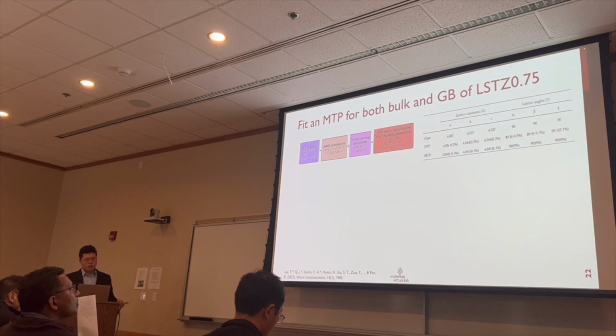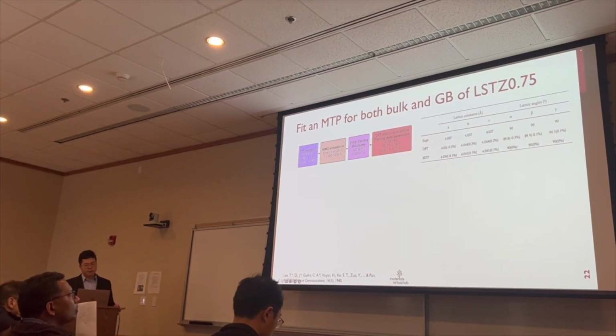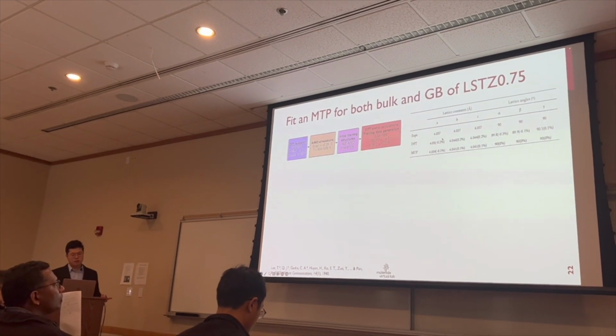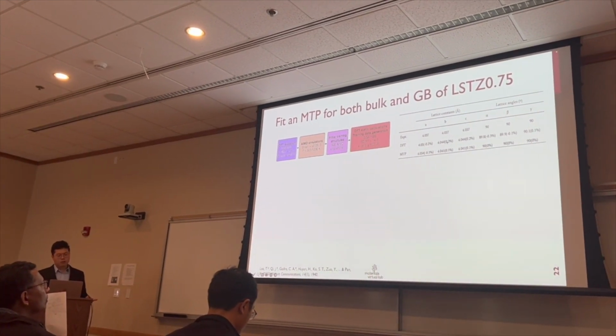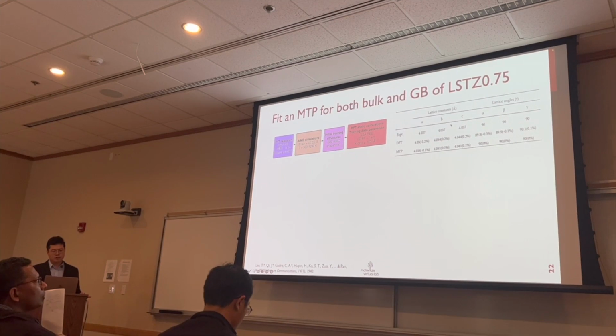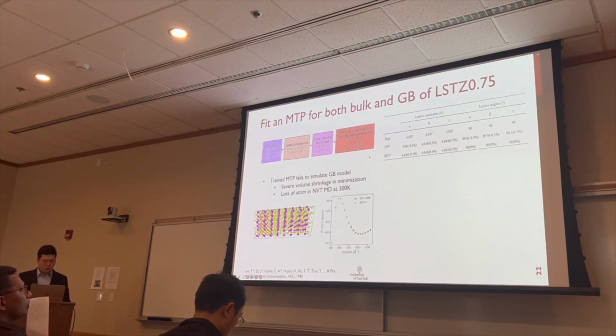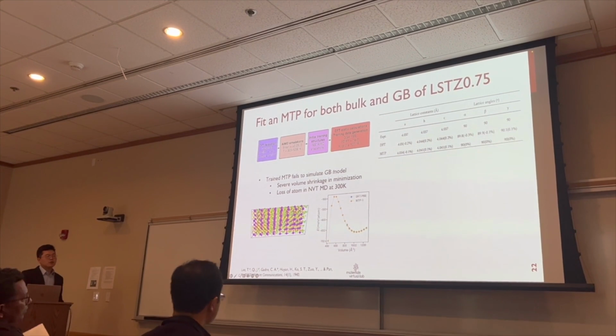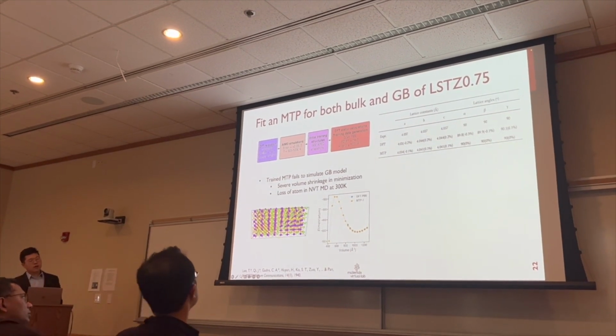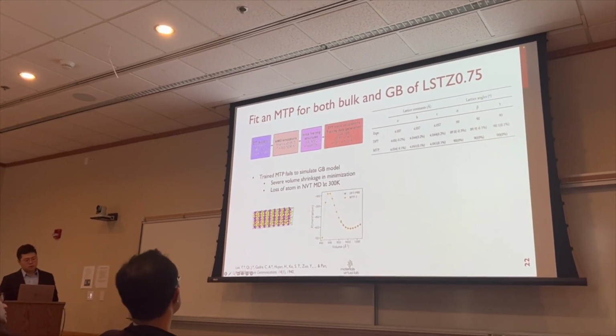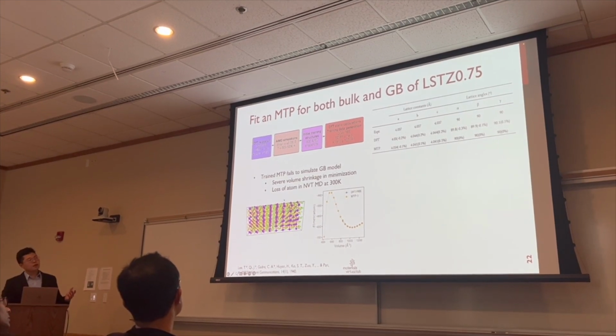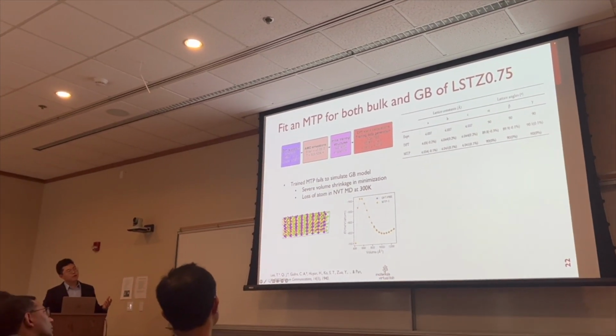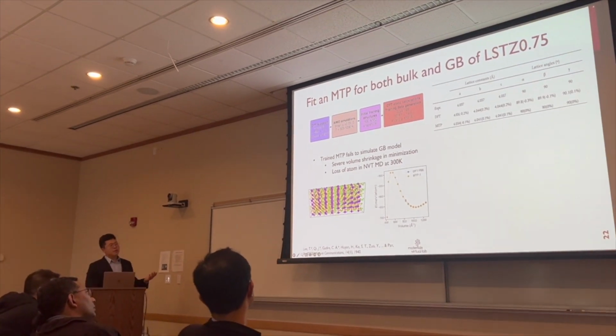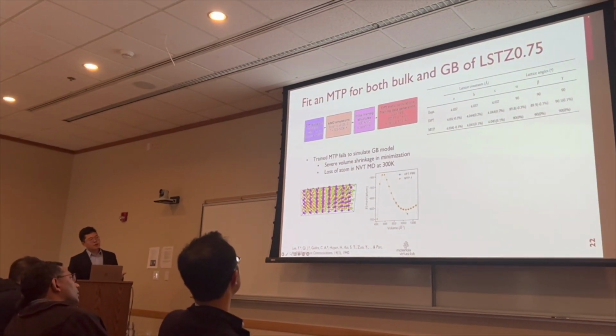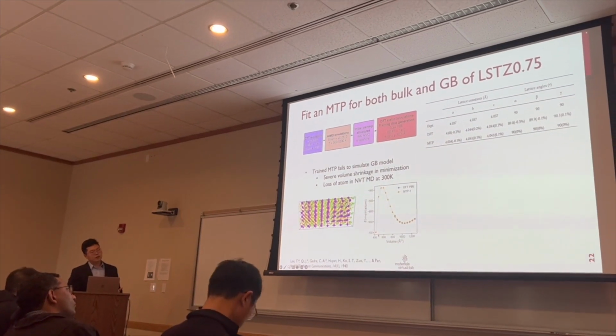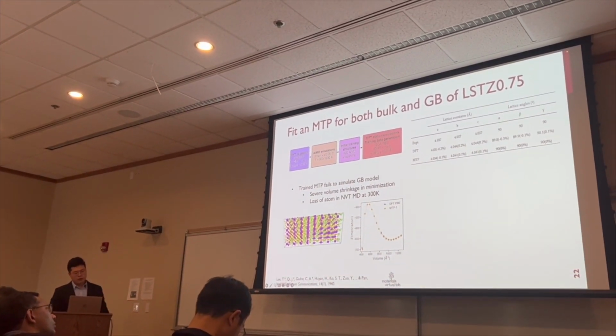And here we use the PBE functional because we see that the DFT result with PBE functional already has very good matching with experimental results in terms of lattice parameters. However, when we apply this moment tensor potential to simulate some practical scenarios, which are grain boundary models, we can see that there's some unphysical behavior. Here is the shrinkage of volume in the energy minimization. And on the right is the equation of state, where it's definitely unphysically low at a shrunk volume.